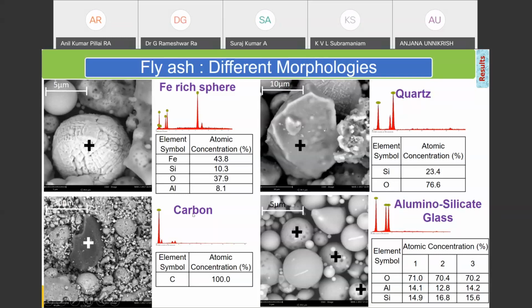There's a lot of unburned carbon in Indian fly ashes, and unburned carbon means two things. One, we are not utilizing the carbon properly, which means the boilers which are used in producing power are not effectively utilizing all the carbon present in the coal. That's why a lot of it is showing up in the ash. The second problem is that if carbon is present, it basically starts absorbing water, it starts absorbing admixtures that we add into concrete, and basically makes those admixtures effectively useless. And that's one of the big challenges in using this fly ash. But fly ash contains these spheres that are present in them. These are basically spheres made of glass. These are alumino-silicate glass. And it is those spheres that we're interested in. These spheres are called cenospheres.